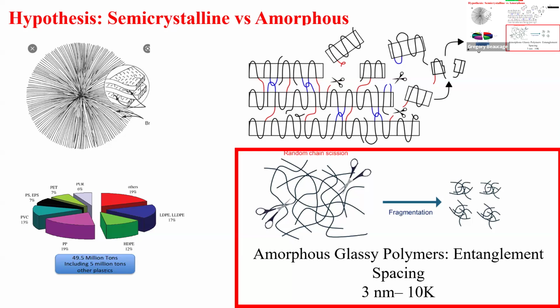But that's actually bad news because if I rub my hand against it, I'm going to get a single layer of polyethylene crystal coming off. And that crystal is going to go in my body. Remember, I told you crystalline silica is worse than amorphous silica. That's where I'm leading with all this, right? So I'm saying the fact that you have semicrystalline polymers naturally, and that's 80% of the marketplace, is guaranteeing that you're going to make these lamellar crystal structures, which are going to persist forever in the environment. And that's what's making micro and nanoplastic. That's why I should be scared. Everybody fine with my hypothesis, or have I lost you all?